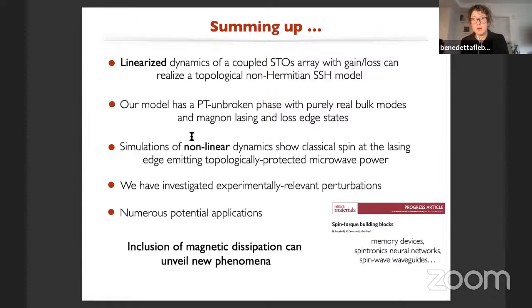So let me sum up this part before I move to the next one. We looked at the linearized dynamics of these coupled spin torque oscillators, and we saw that if we judiciously tune gain and loss, we can realize a non-Hermitian SSH model. We saw that this non-Hermitian SSH model can support a lasing edge state, and this lasing edge state, this magnon with the positive imaginary energy, really has an effect on the classical nonlinear spin dynamics. We looked at experimentally relevant perturbations. I think in general, topologically protected microwave emission in this type of spin system can definitely find many applications.